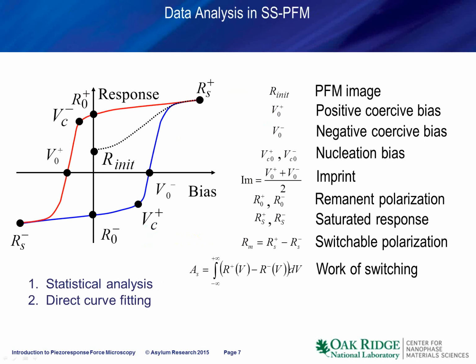Obviously, working with such a data set is rather complicated, so what we want to do is reduce this data to the form of two-dimensional images that we can visualize and hopefully understand. In order to do this, we can phenomenologically describe the hysteresis loop, so introduce parameters such as positive and negative remnant polarization, parameters such as coercive bias, parameters such as the nucleation biases, and parameters such as work of switching, or area under the hysteresis loop.